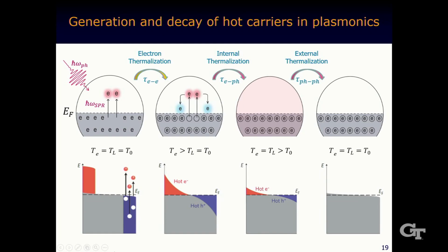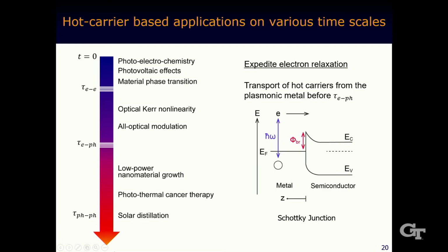One way for us to suppress this electron-phonon scattering and speed up the response is to form a Schottky junction. For example, the metallic structure is placed next to an electron absorber, which is some type of semiconductor, with a Schottky junction in between. In this case, we produce one additional channel for electrons to escape. Electrons in the metal don't have to exchange their energy with the lattice in the metal. Instead, they can get expelled or climb over the barrier and then reach the semiconductor. This process can be much faster than the intrinsically slow electron-phonon scattering.